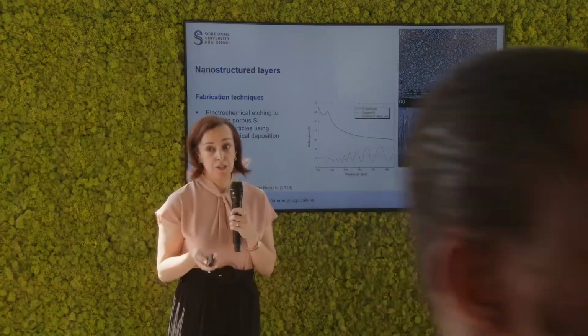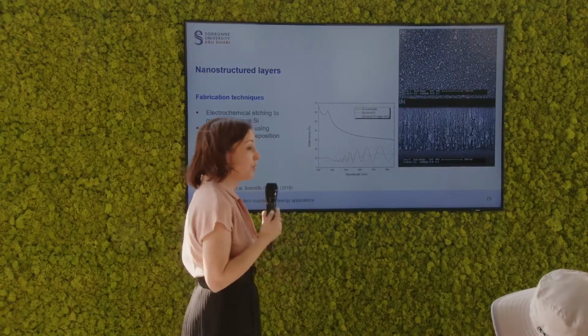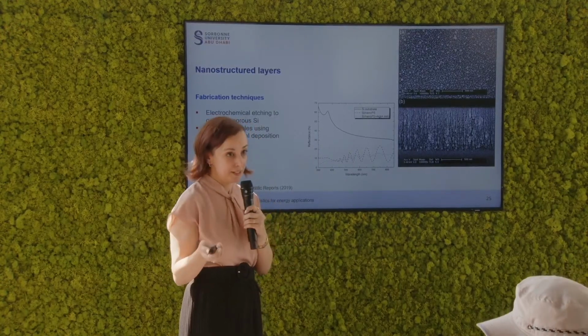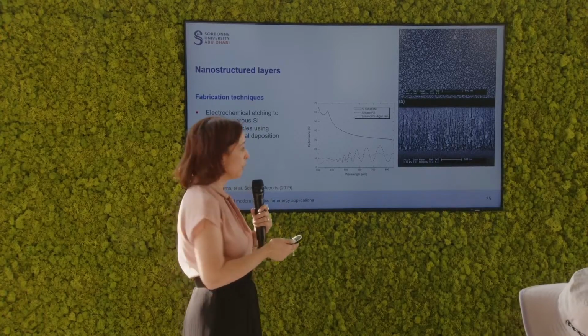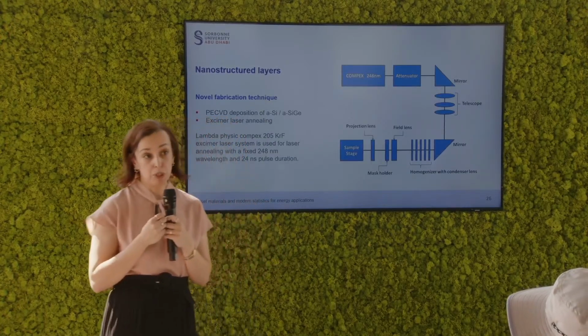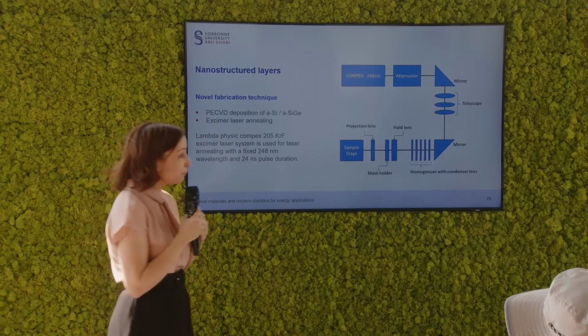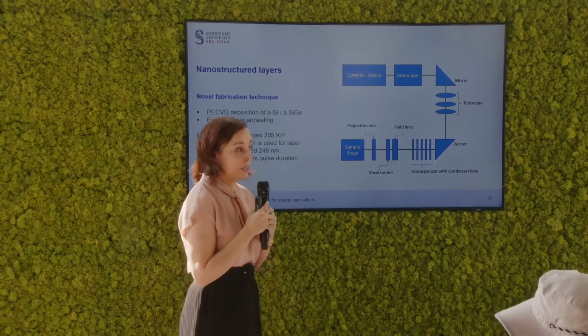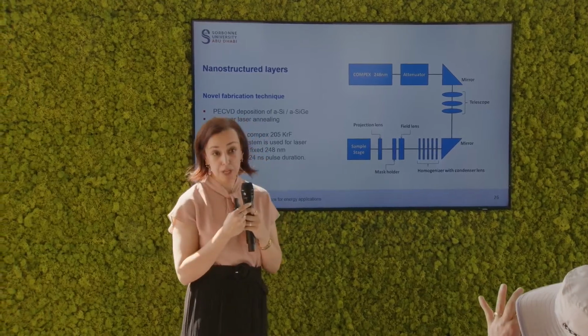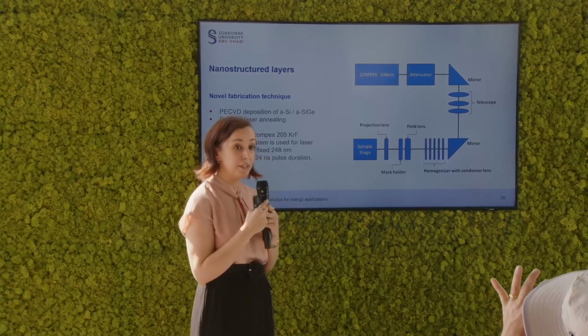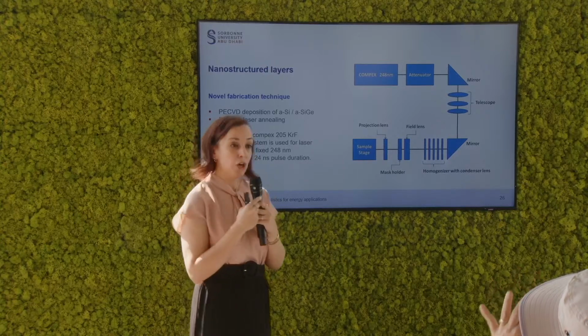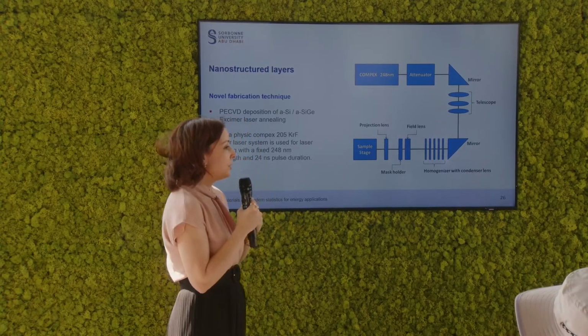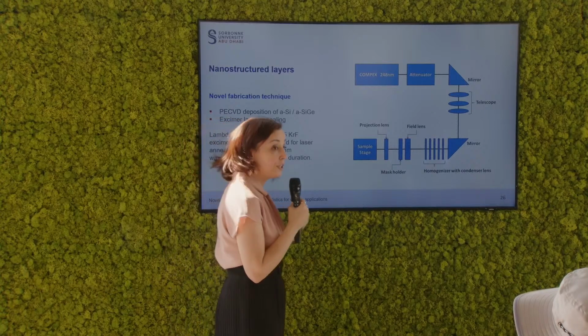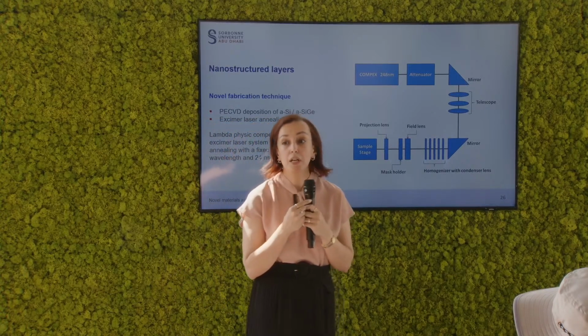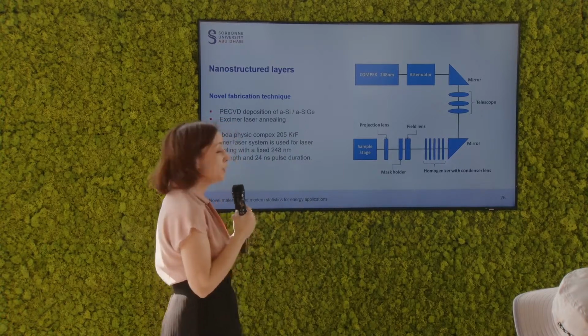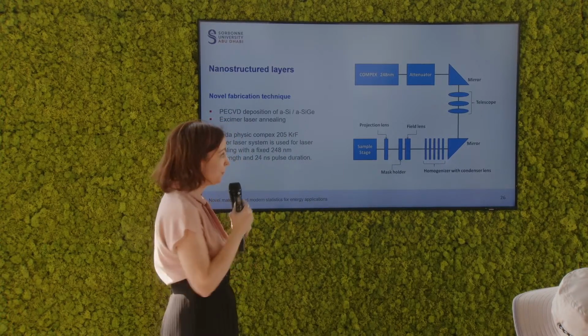So what we are suggesting for our particular fabrication process, for both silicon and silicon germanium, both of these materials would work with our process, is to use an excimer laser annealing of the material. So we use an excimer laser, which generates a fixed wavelength of 248 nanometers. So you're in the ultraviolet range. The laser is then connected to an attenuator, which allows you to control the energy of the pulse generated, and you can generate a single pulse or multiple pulses for that laser.